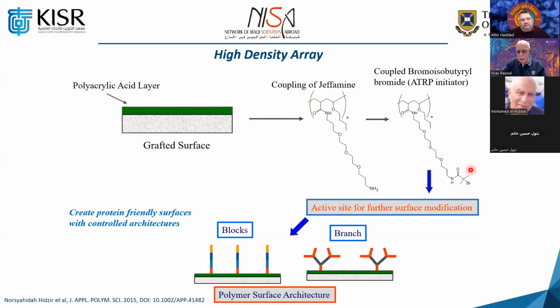And of course, afterward, we put an ATRP initiator. This is the ATRP initiator here, where we will be able to start controlled free radical polymerization onto that surface. So you have the acrylic acid attached to Jeffamine with the amine, and then we added this initiator, and from that initiator we will be able to build up different architectures. So we prepared block copolymers, we prepared branched copolymers, and a variety of surfaces. And of course, all these polymers you choose to be useful for a variety of applications. And with this architecture, we found some unique characteristics, on which I will probably give you some results.